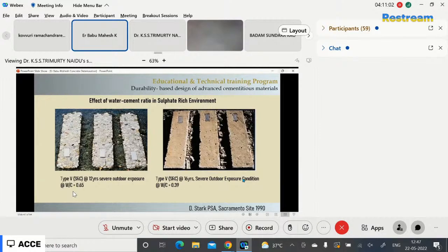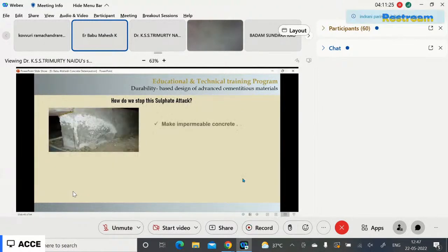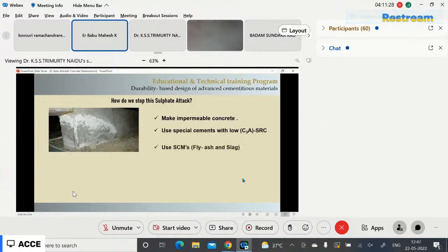We observe that both the beams have been made with different water cement ratios and exposed to sulfate. Even though we have used SRC cement, we found that the 0.65 water cement ratio beams have deteriorated. At the 0.39 water cement ratio, the beams have not deteriorated as fast compared to the 0.65 water cement ratio. How do we stop this sulfate attack?